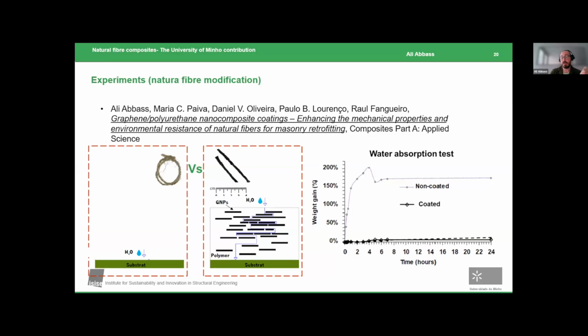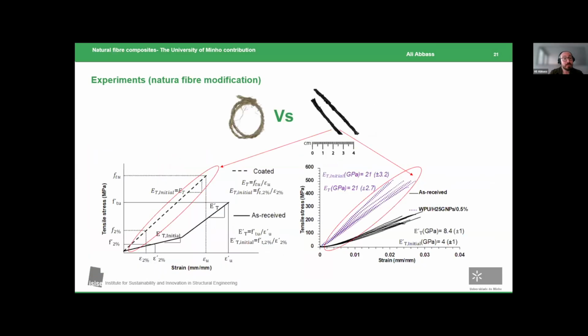It's not super hydrophobic. It's not hydrophobic either. It's water resistant. This is due to the so-called barrier effect. You would have the graphene nanoplatelets aligning in a sheet-like manner, and this would slow down the propagation of the fluid through the polymer to the substrate of the natural fiber.